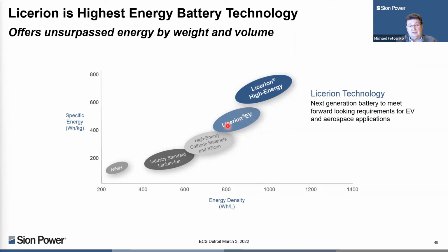We see our initial energy, the products that we're making now are 400 watt-hour per kilogram. But as we increase that footprint, going from 10 by 10 to 10 by 30, the energy is going to go up to 500 watt-hour per kilogram in that design. We have aerospace designs that are even a little bit higher. Let me show you that.